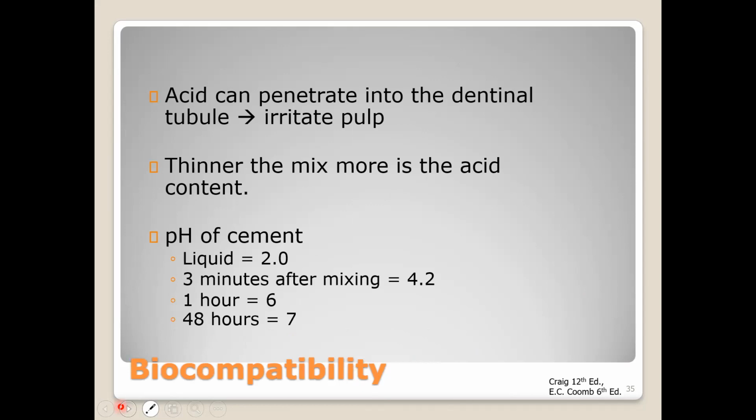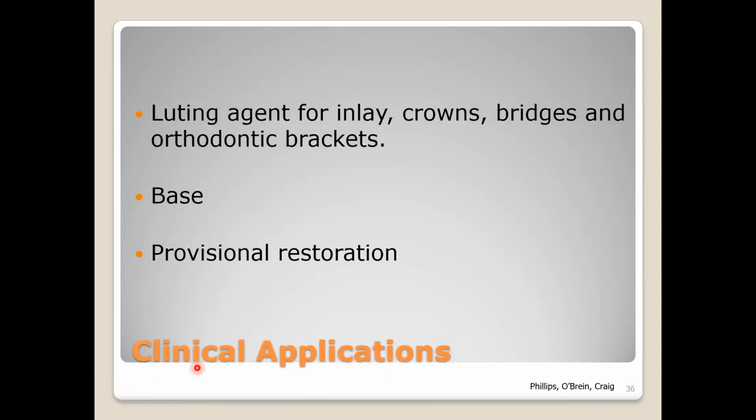So the pH of the cement liquid is 2. 3 minutes after mixing, it comes up to 4.2. At 1 hour it is 6, and almost 48 hours after it comes back to 7. So this is one of the causes for the pulpal irritation. You have a freshly cut dentine surface, and then you're going to place something which is highly acidic and has an initial pH of 2 to 4, then it is going to cause some sensitivity.